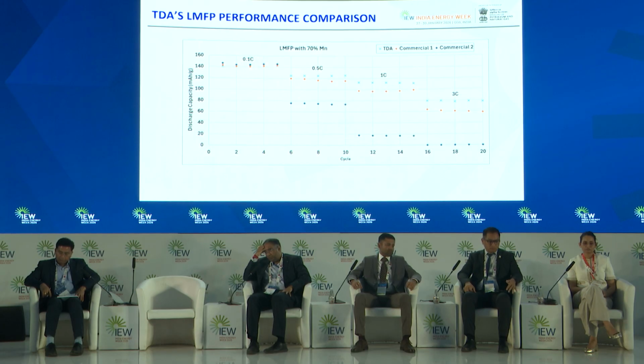So we have a stable capacity and an energy density of about 155 to 160 watt hours per kilogram, which is about 10 to 15% higher than the energy density of LFP pouch cells. This is the LMFP performance comparison with our material and two commercial materials. These are different cycling rates, 0.1C being the most favorable, all the way down to 3C. And as you can see, the performance of our material appears to be much better than what you would find with commercial materials.